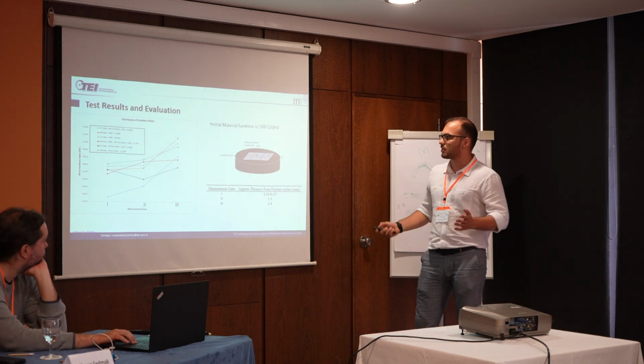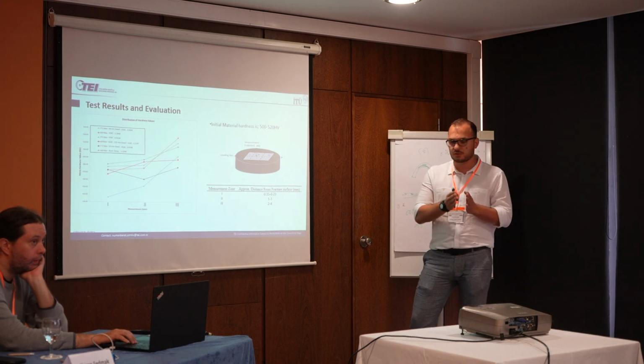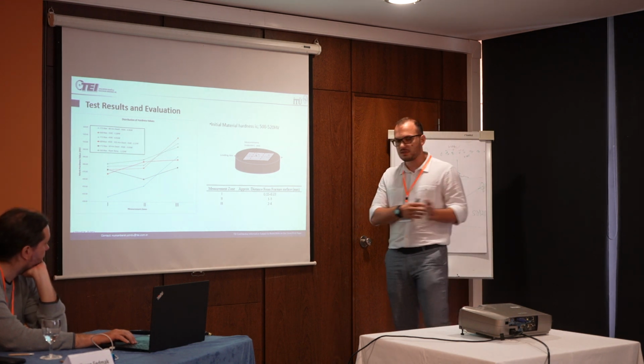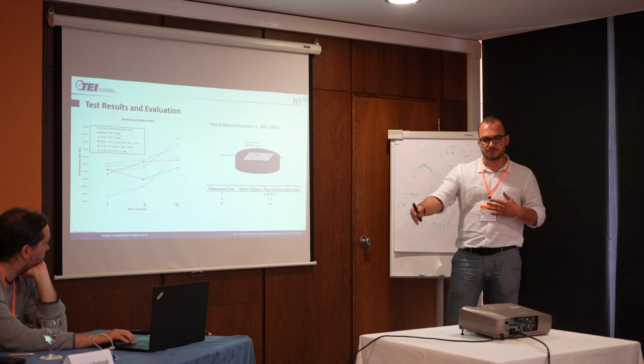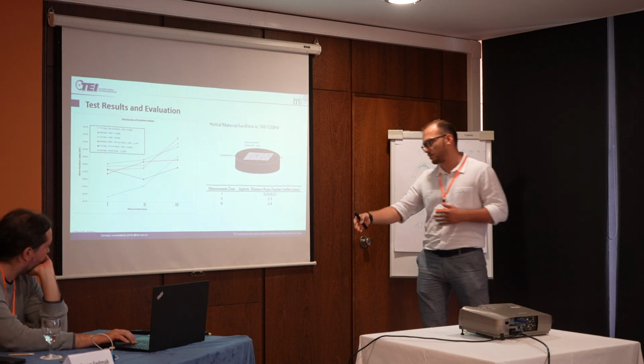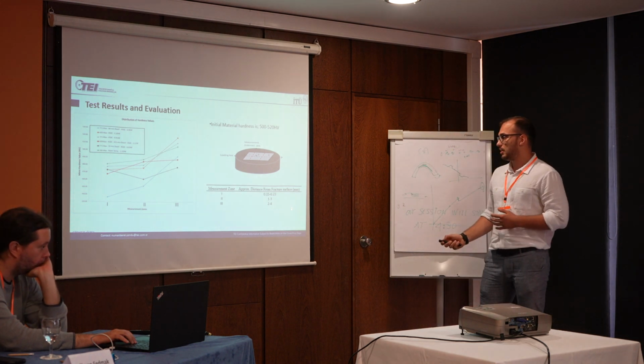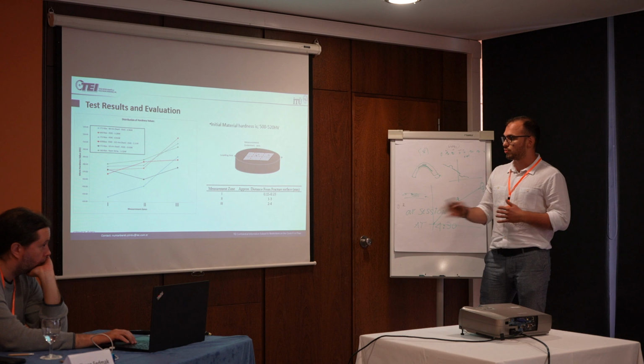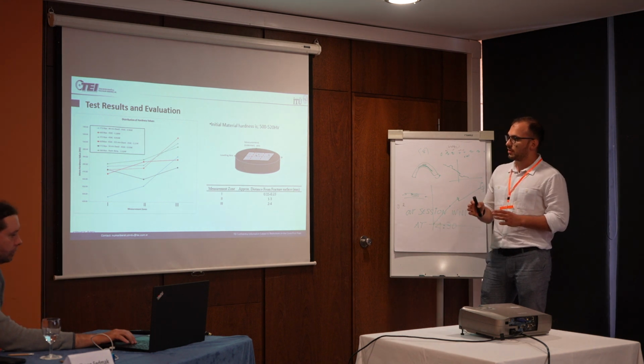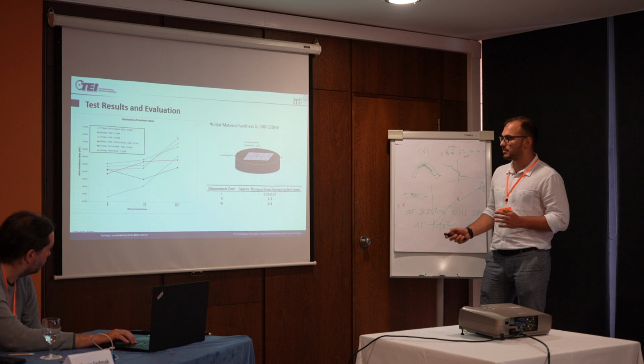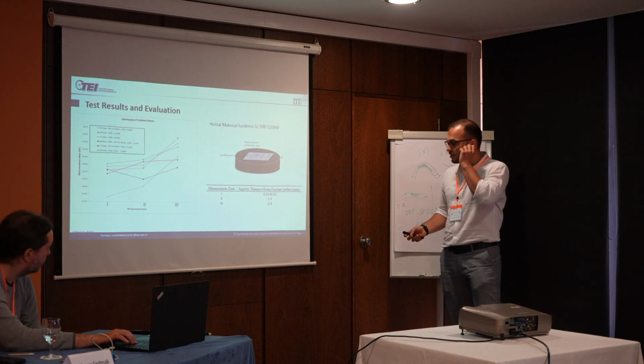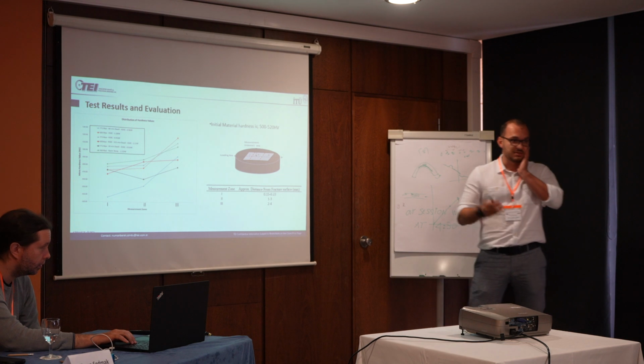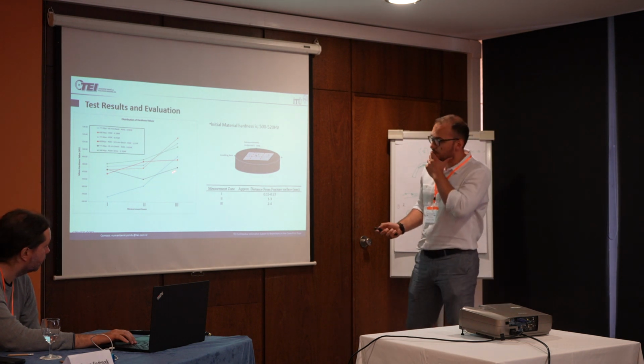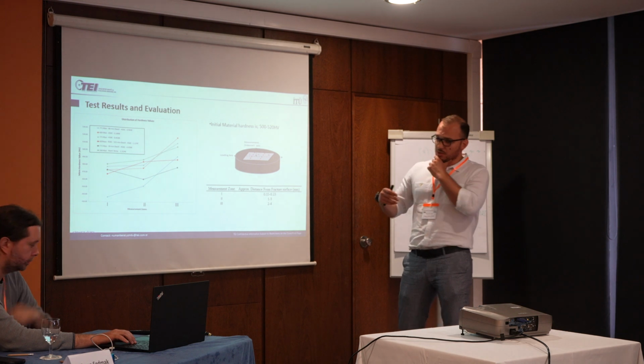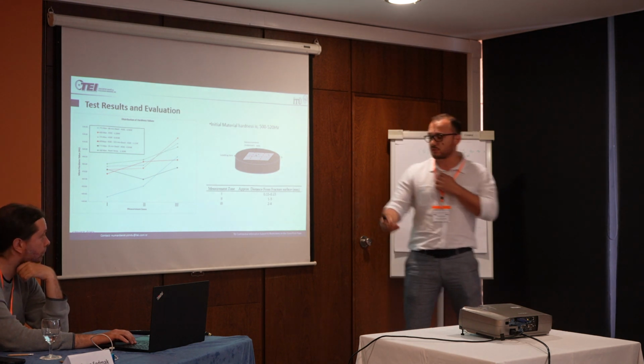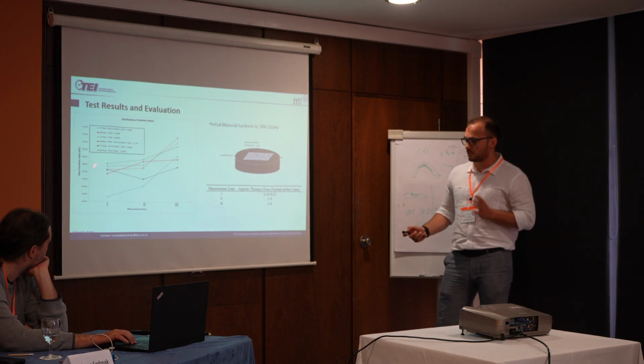These regions are basically near the fracture surface, a relatively medium range from the fracture surface, and the outer regions, which are 2 to 4 millimeters away, and the measurements near the fracture surface have distances of about 0.15 to 0.23 millimeters. So here we see that from the far side of the specimen to the fracture surface we see a softening.